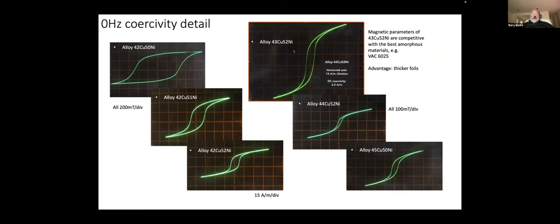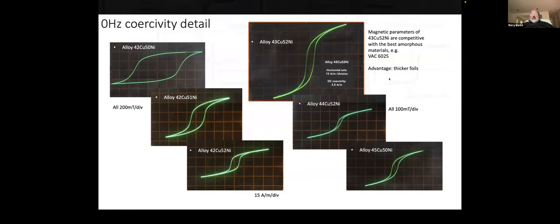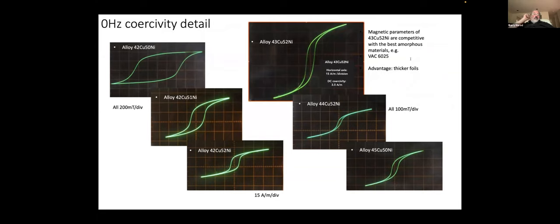This one here, 43% and 50 copper, 52% nickel, has a BH curve about as close to the vacuum smelt, some amorphous materials that are being used for a lot of sensors now, as close to that as I've ever seen. Coercivities of 3.5 amperes per meter, which is nominally smaller than what the vacuum smelts produce. Very low noise material, comparable saturation moment, comparable Curie temperature. It has one big advantage over the vacuum smelts material: I can make this any thickness foil I want, whereas the amorphous materials are limited, because of how they're manufactured, to thicknesses below 20 microns.